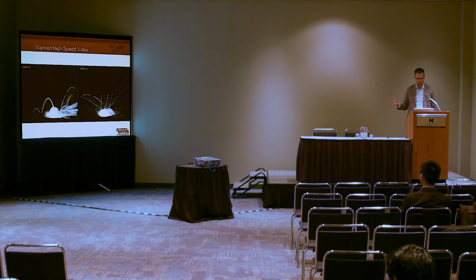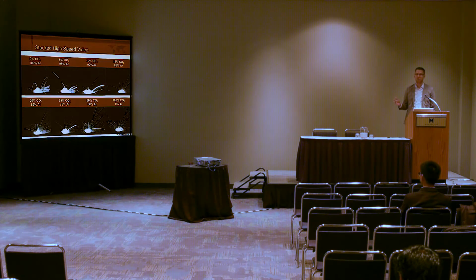And so, here's the 100% argon, the 100% CO2. So the 2 videos I showed before. Before you could sort of make out what was happening, this gives you a really clear picture. Spatter is much higher on the 100% CO2. It goes in more directions. 100% argon, you can see that there's a higher arc length. Spatter's very consistently moving to the right, but there's less of it. And so when you look at all of them, you can see these trends.